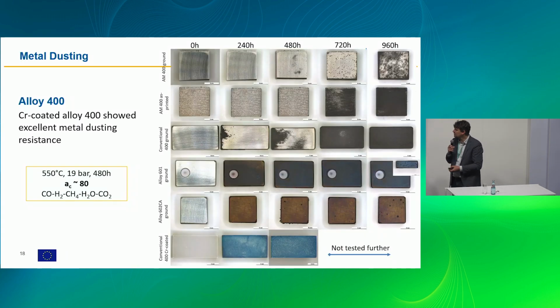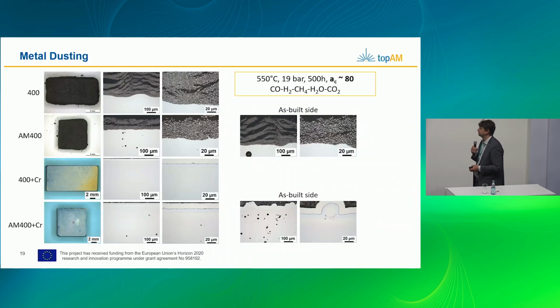And then basically so far, this is the bottom. This is currently continuing this exposure, but we are very hopeful that basically by this combination we can completely prevent the metal dusting. And now the idea is basically, since we need a post-processing anyway, to combine this with the coating technique, to first pick also the right post-processing, and especially in harsh environments that might be key if your part fails or can last much, much longer.